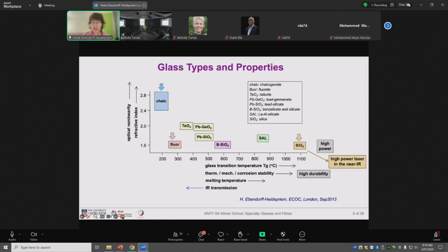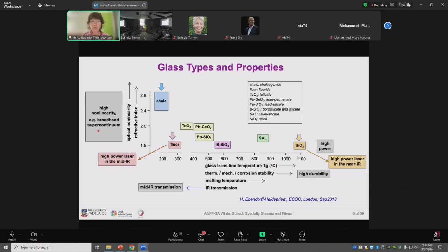On the other side, we have the chalcogenide and fluoride glasses. They have the mid-infrared transmission. However, that means they also have low glass transition points and therefore lower durability. However, for the fluoride glass, nevertheless, the advantage is not only the mid-infrared transmission, but the low index and therefore high-power laser applications in the mid-infrared. We'll give examples there. And for the chalcogenide glasses, they show the so-called high nonlinearity, which is of importance for the so-called supercontinuum generation.